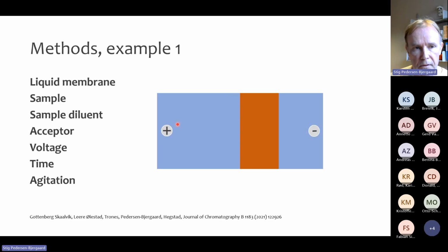To build up the method, we need to define the chemical composition of the liquid membrane. We need to define the sample and also the sample diluent, because normally we dilute the sample a little bit with buffer to control pH in the sample. We also had to define the acceptor. We had to define the voltage, the magnitude of the electrical field. We need to define the extraction time and the agitation rate.